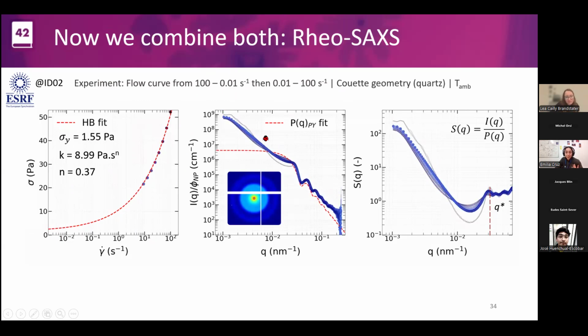But what you can see here is that we have linked the structure at the same time as we do the experiment. And now, as we are going to the low shear rates, because now you're familiar with all these characteristic shapes, if you see your structure factor, you see basically that there is this correlation hole, and now we're going for higher shear rates, and the correlation hole disappears. So let's do it once again. So the experiment will begin now.